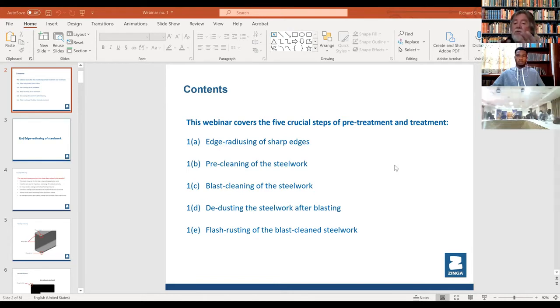But edge radiusing on new steel is vital, because what happens is if you apply Zinga or paint onto a sharp edge, which is a 90-degree edge, as it dries, it pulls back from the corner. So if you're taking measurements, you'll be getting, say, 100 microns on the flat, but on the corner, you're lucky to get 50 microns.